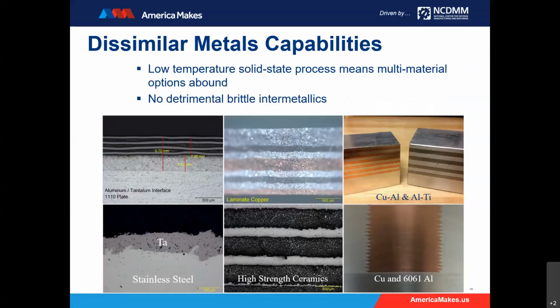So we've looked at some of these pictures in another slide, just reinforcing the idea that dissimilar metals are a large part of what we do, mixing materials, doing things like cladding, in the center of a part, adding features with specific metals. We've printed materials that have a custom coefficient of thermal expansion, or materials that have a variation in CTE over the Z height as we print. So we change our layering structure as we go up so that we can have a variable CTE or a variable modulus through thickness. And that's all possible because we can weld these dissimilar materials.